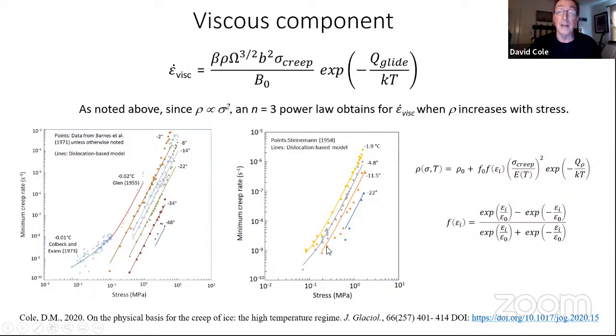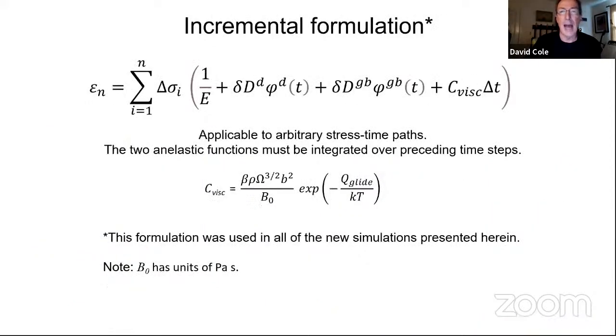And the interesting thing here is I mentioned that if the dislocation density doesn't change much, then you don't get n equals 3 behavior. That's what you're seeing going on down at the low stresses in these two plots or high temperatures here. As long as the dislocation density is increasing, you wind up with this fairly n=3 behavior, and then that falls off to something approaching linear behavior down at low stresses because you're not increasing the dislocation density very much. All right, so there's that.